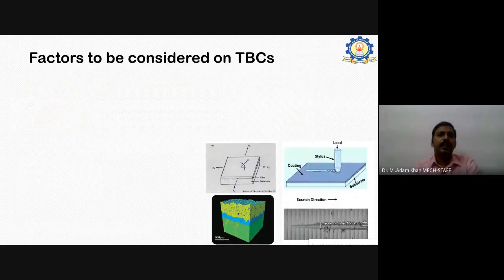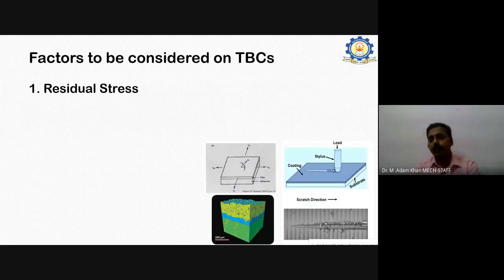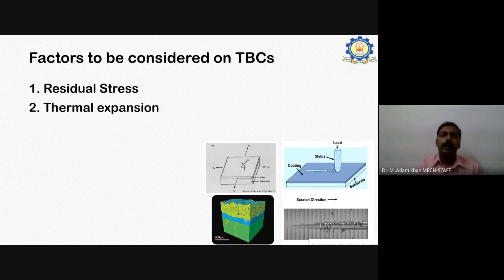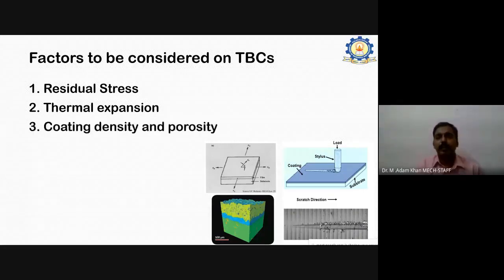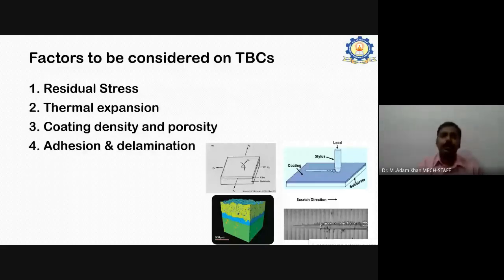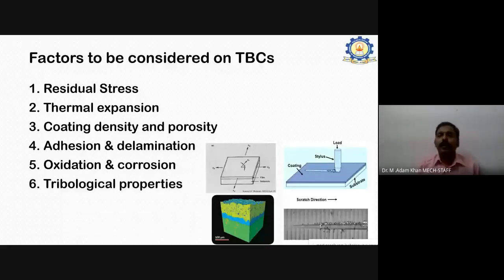So while making any thermal barrier coatings, you should keep some points in mind. One is residual stress, because of heating or any sort of thermal loading. It should not have a residual stress. Next is the thermal expansion factor, coating density and porosity and how to reduce it, then adhesion and delamination, oxidation, corrosion, tribological properties. For example, when we are talking about this, when it is a bulk, if I'm talking about this one, see, this has two layers here. When it is projected in three dimensions, it has two layers, just like this.